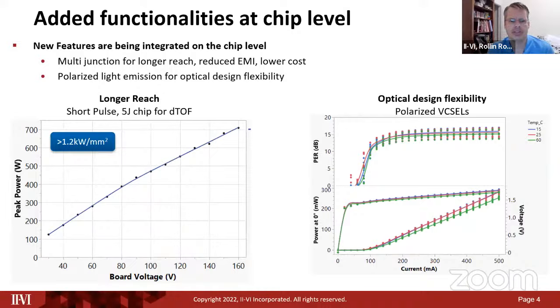Again, in some cases they want to do multi-channel, so you're going to need these high powers on individual emitters. So there may be a push. There's also a push to get these emitter sizes up, 20, 30, 40, 50 microns instead of the standard 10 microns for some of these high-powered arrays.